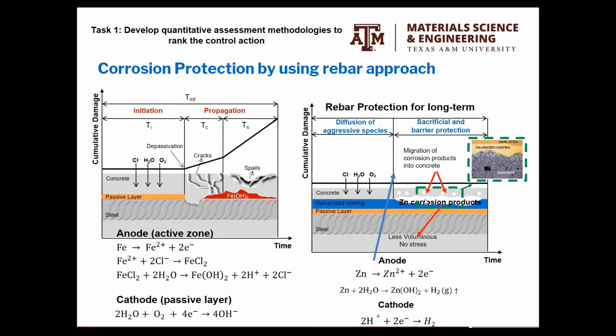And we are doing this characterization that the corrosion products are more uniform than this. And you see the schematic, these are very heterogeneous, very thick. In here is more homogeneous. That's why we are saying that the cumulative damage still is on stable state. And after a certain point, let's say now, this will be the activation time for this schematic.